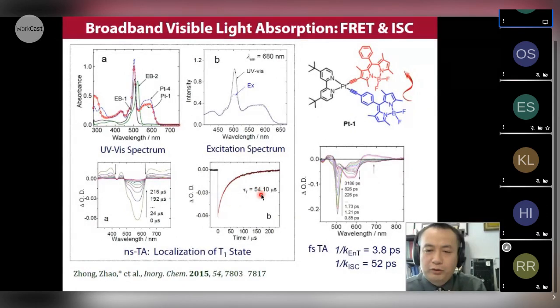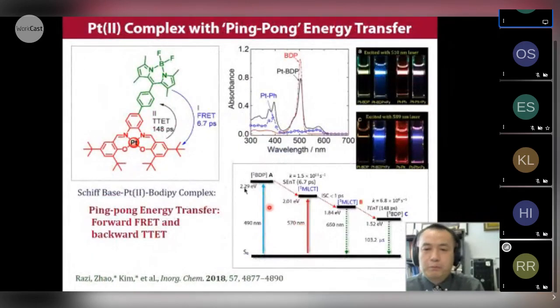With some routine spectral studies, we confirm the complex shows a broadband absorption and the singlet energy transfer and the long-lived triplet state localized on this red part, not the blue one. We also confirmed that the singlet energy transfer takes about 4 picoseconds. The intersystem crossing of the red part takes about 50 picoseconds.